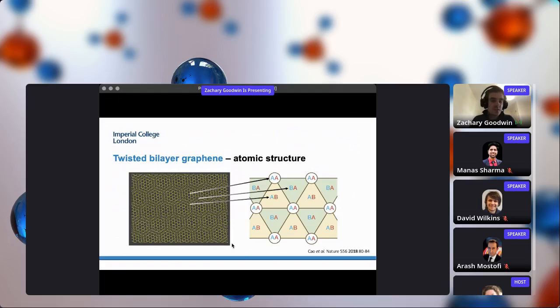So to create the material, what we do is we stack 2 layers of graphene on top of each other. And so we can start from an AA stacked bilayer graphene, and we can introduce a relative twist angle between these 2 graphene sheets to create this emergent moiré honeycomb pattern. And this moiré pattern is characterized by a stacking sequence which varies throughout real space. So as you can see, in certain areas of space, we have AA stacking between these bilayers, but in other regions of space, we either have AB stacking or BA stacking.